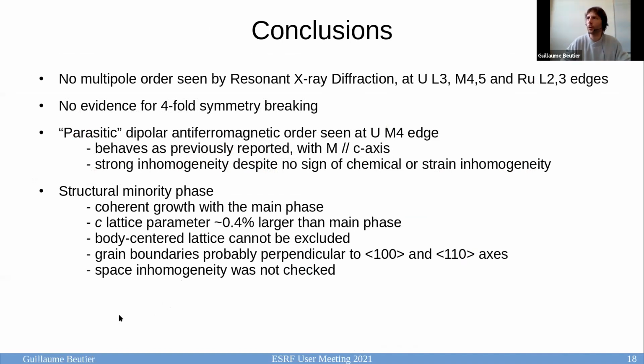So I'm coming to the conclusions, and as you see, I have left many open questions. We didn't see any multipolar order by resonant X-ray diffraction at the many edges we looked at. We also didn't see any evidence for fourfold symmetry breaking. But what we saw is that the parasitic dipolar antiferromagnetic order is very inhomogeneous on the sample, despite the fact that we didn't have a clear sign for strain inhomogeneity or chemical inhomogeneity. And the other interesting finding is that we found in our sample a structural minority phase, which grows coherently with the main phase and has a slightly different C lattice parameter.